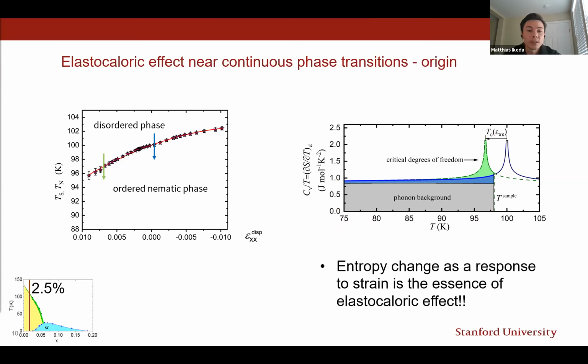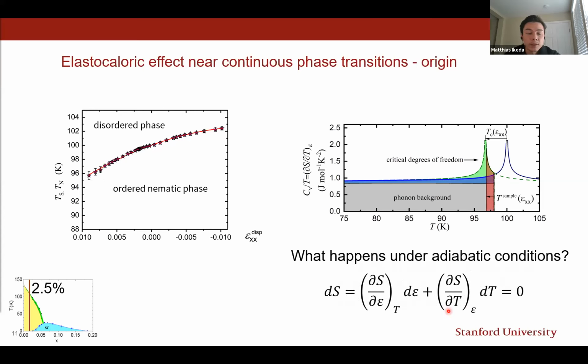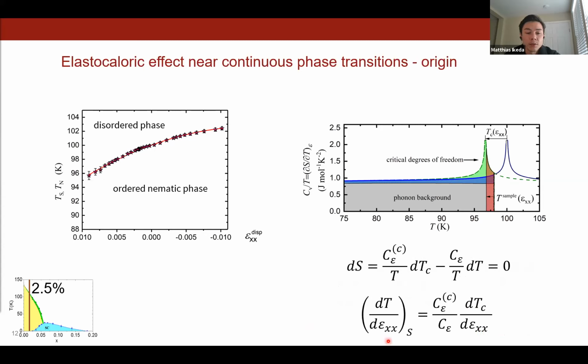And now an entropy change as a response to strain is, of course, just the essence of the elastocaloric effect. And so now we understand why there is an elastocaloric effect in the vicinity of continuous phase transitions. Under adiabatic conditions, again, we expect the balancing contribution that's originating from a temperature change. And this balancing contribution is shown as the red area here. And rewriting this equation, we find that the elastocaloric temperature change as a response to strain is proportional to the critical part of the heat capacity divided by the full heat capacity, and the proportionality constant is nothing else than the strain dependence of the transition temperature itself.